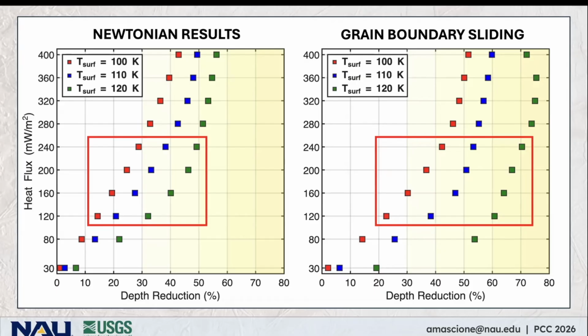And in almost every case, we're seeing at least 30% relaxation, with the highest heat simulations resulting in up to 70% depth reduction. So if we assume that grain boundary sliding is the dominant deformation mechanism in the crust, and that Europa has experienced high heat events, then it's very likely that viscous relaxation has played a significant role in post-impact shallowing. However, we can't be certain that GBS is the dominant deformation mechanism here, as this depends on things like grain size and impurity content within the crust, which are currently not well constrained for Europa.